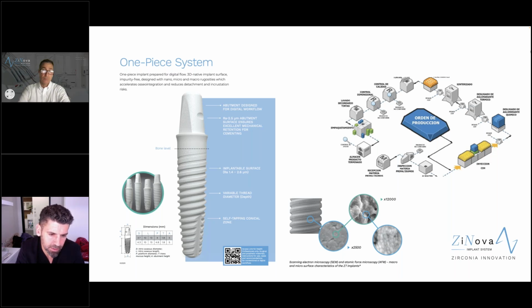It has a variable thread diameter, and it is a self-tapping conical design. The tissue level portion above the bone level is a 1.8 collar of polished or smooth zirconia. And then the abutment, which is designed for digital workflow, has a roughness of about 2.5 microns, and this facilitates the mechanical retention for cementing. Again, it's manufactured by ceramic injection molding, and because of that, the roughness is already embedded in the mold.